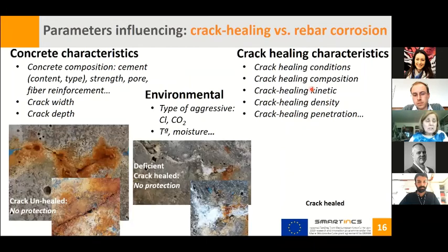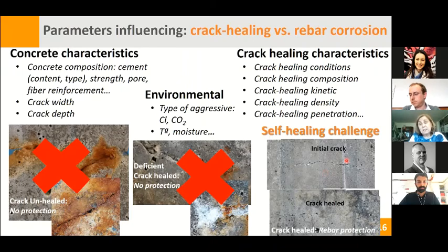So clearly what we are not interested in is that we have a crack, and if there is no healing process of this crack, clearly the rebar is not protected and the corrosion will be initiated. However, we can have a healing process of the crack, but this healing is not enough to protect the reinforcement, and the corrosion is again initiated. However, we can have a final step, and that is the challenge of smart and self-healing with regard to corrosion: although we have a crack, this cracking will be healed in such a way that it is able to protect the reinforcement, and corrosion will not be an issue.